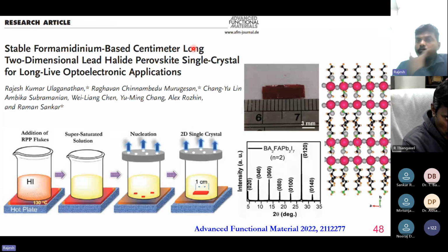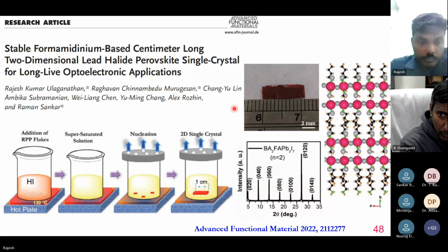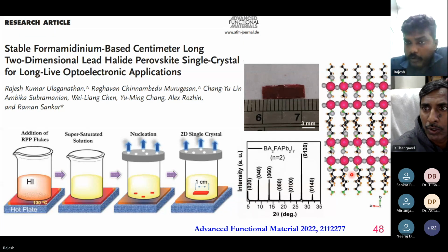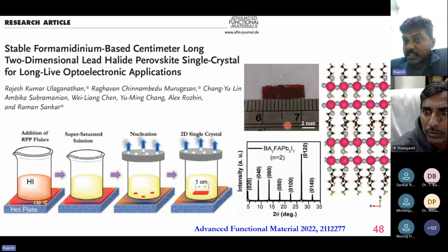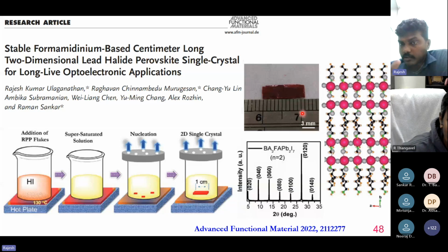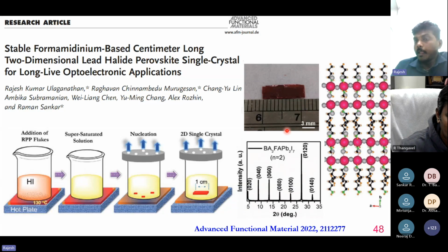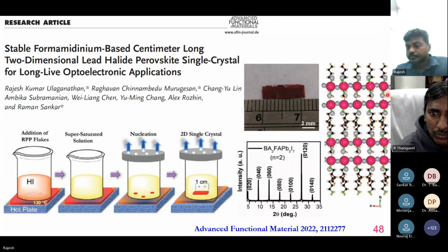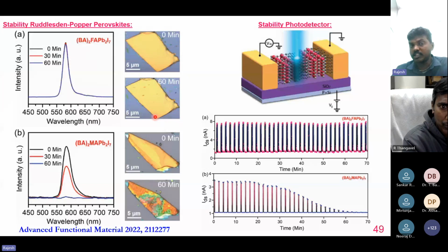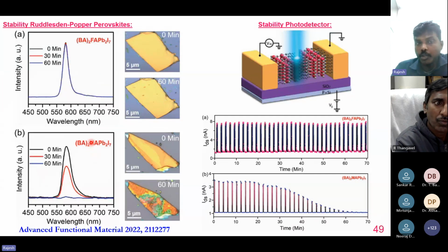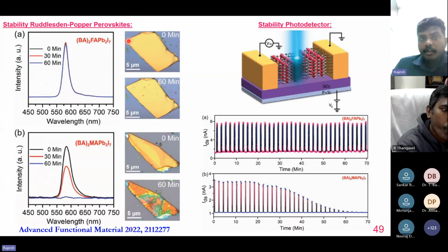So in this work, for the first time, we demonstrated growing a very large single crystal using a solution growth technique. We grew almost 1 centimeter size formamidinium butylammonium based lead iodide perovskite, and showed it has very good, high crystallinity and a very strong stability as compared to methylammonium based perovskites. So you can see in the optical image and the photoluminescence.